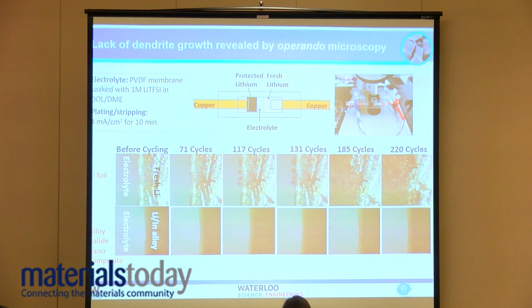So the proof is in the pudding, or in the pictures in this case. We've used operando microscopy to take a look at the cell over 220 cycles. This is in the case of just lithium, and this is the alloy film. And you can see that after about 131 cycles, we start to see pulverization, which is classic for lithium films, and finally complete decrepitation of the surface in dendrite formation, whereas in the case of the alloy halide composite film, there's absolutely no change in the surface.